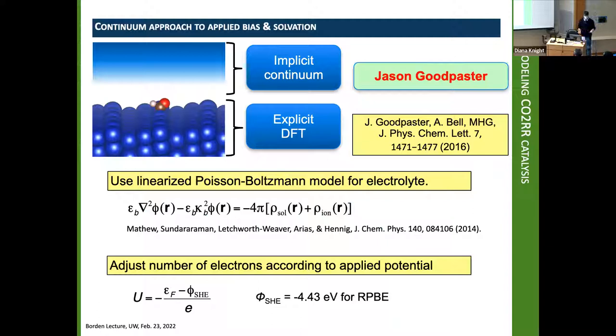This is mostly an applications talk, but it has not been routine to do applied bias in density functional theory calculations. So I owe you a slide or two to tell you what we do. Because we're charging the electrode, we then use a continuum solvation model, continuum solvent and electrolyte. That is the so-called linearized Poisson-Boltzmann model that provides the countercharge. In other words, the electrolyte will provide positive ionic density coming towards the negatively charged cathode. And we adjust the number of electrons in the calculation to match the applied bias.